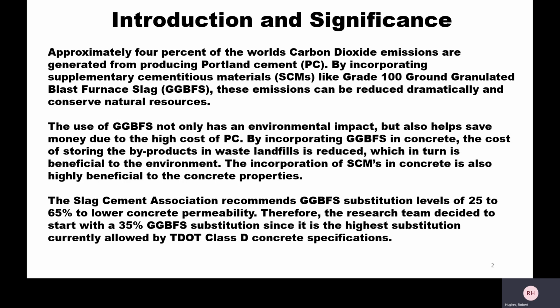Now, the use of GGBFS not only has an environmental impact, but can also help save money due to the high cost of PC, because this slag is actually less expensive than PC. So by incorporating this slag in concrete, the cost of storing the byproducts in a waste landfill is reduced, which is in turn beneficial to the environment as well. And the incorporation of SCMs also has a very significant impact on hardened concrete properties that you'll see later. The Slag Cement Association recommends GGBFS substitution levels of 25 to 65% to lower concrete permeability.